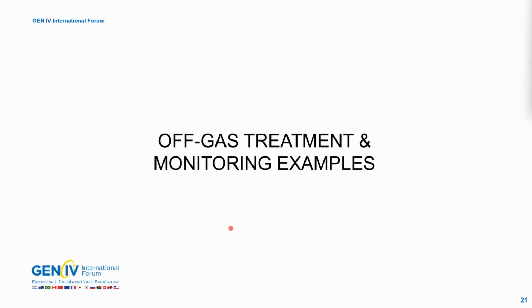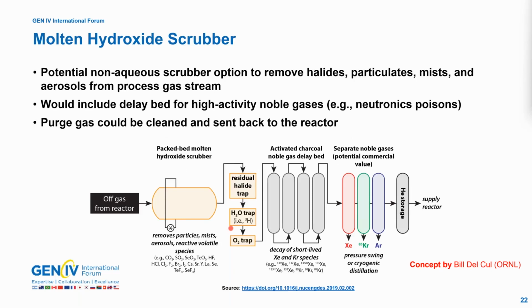So now I'll talk about off-gas treatment and monitoring examples. I alluded to the molten hydroxide scrubber earlier. This is a really interesting concept proposed by Bill Del Cul at ORNL, where the initial system is a packed bed molten hydroxide scrubber using some sort of an alkali hydroxide eutectic salt. This is non-aqueous, so it's running at, say, 300, 400 degrees Celsius.